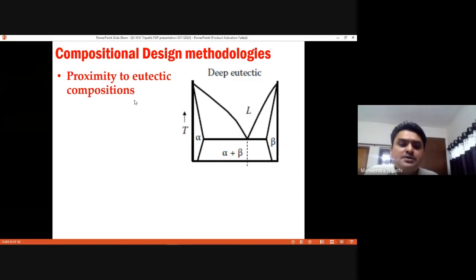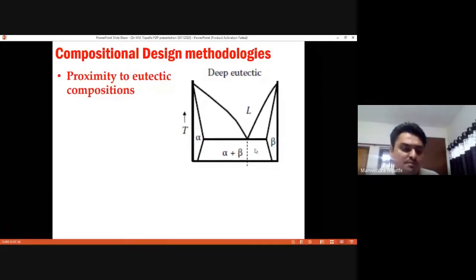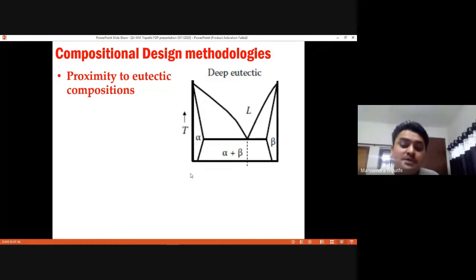So this is one technique, right? And it is heavily relied upon to date. Since 60 years of research, people are still looking for compositions with a deep eutectic. For the binary system, there are many reported phase diagrams. Even many ternary phase diagrams, for the three element system, are available. But if you go for a 4-component system, it is very difficult to visualize. You cannot visualize it, and many 4-component phase diagrams are not available, right? And if you go for higher component systems, 5, 6, 7, 8, we cannot easily predict the eutectic composition. That is why we need certain techniques by which we can predict it, and try whether it has high glass forming ability.